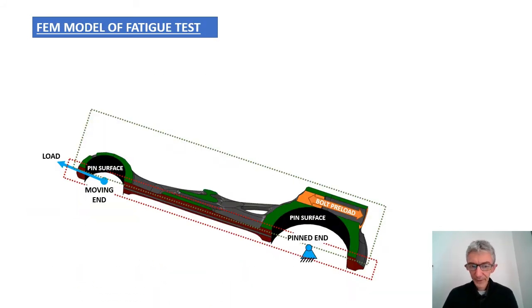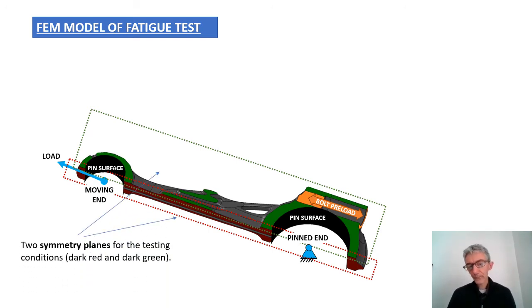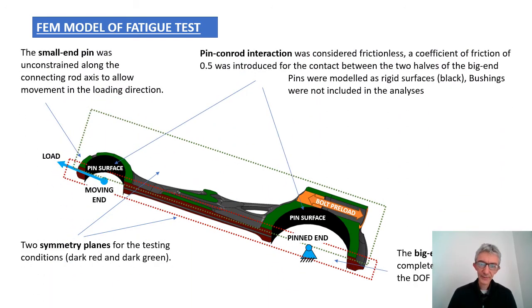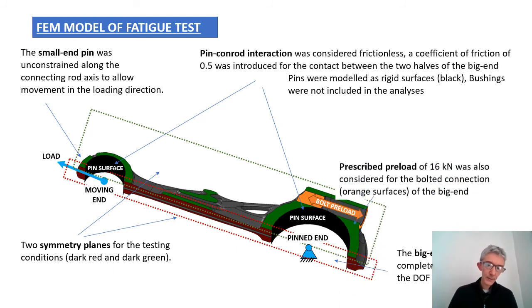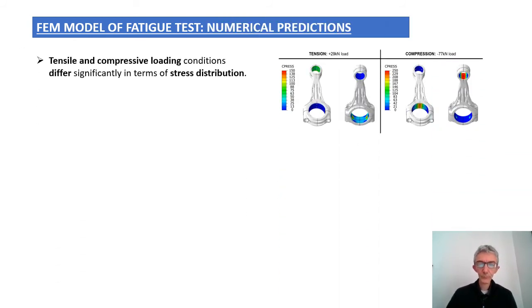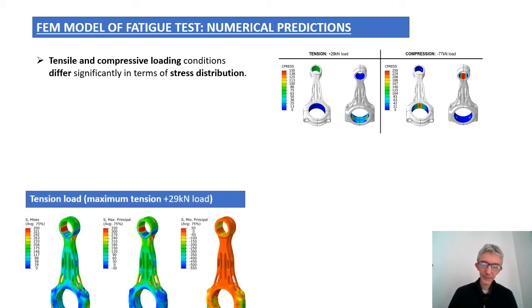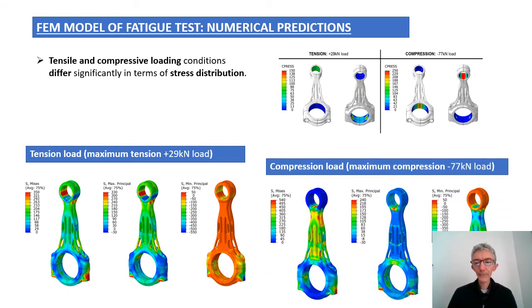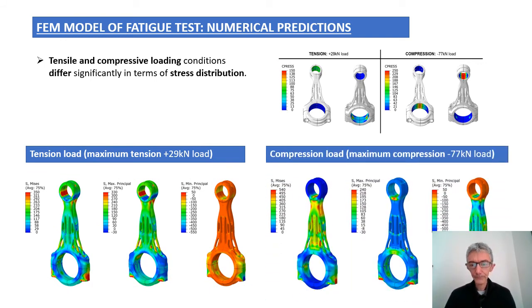In parallel with fatigue testing, we also implemented a finite element model of the fatigue test, and in this model, a very important aspect is the inclusion of the contact interaction between the conrod and the pins that were modeled as analytical rigid surfaces. Because as a consequence of this interaction, when switching from tensile to compression load phases, there is a change in the distribution of contact pressure, and as a consequence, there is a different stress flow within the branches of the conrod, so the contour maps in the two phases are quite different.